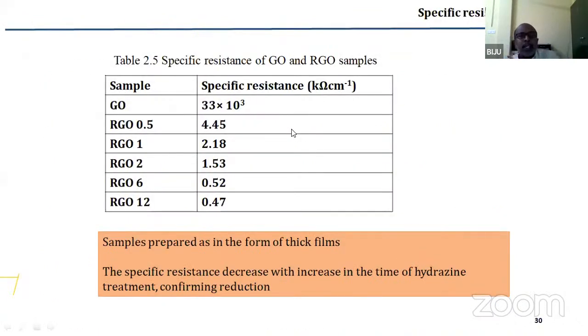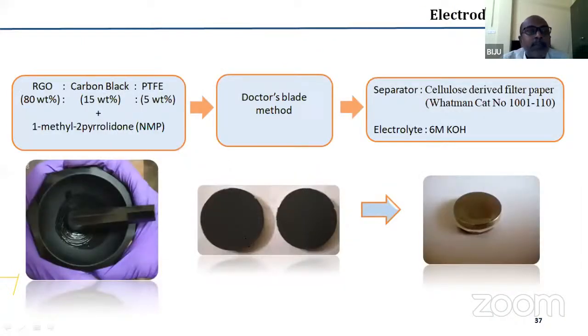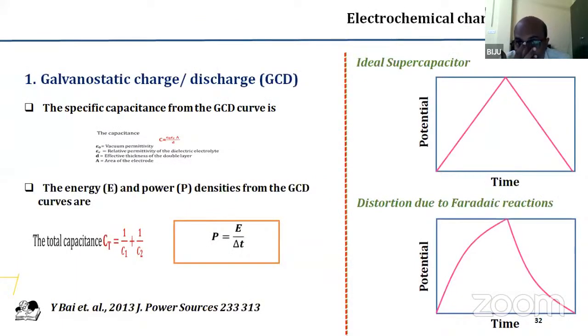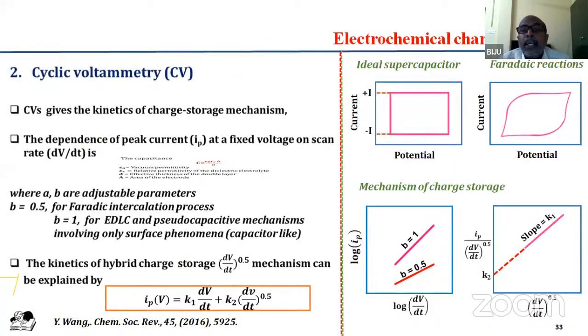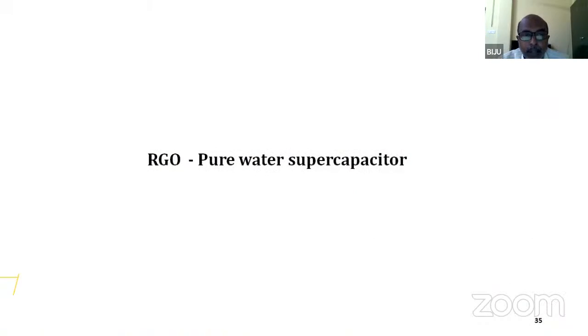Now the specific resistance of these samples was also measured, and as expected during reduction, the specific resistance gradually decreased because the graphitic layers were becoming more and more conductive. Now, the supercapacitor electrodes were produced in the very conventional way. The images are shown. I will skip the characterization techniques for supercapacitors. We use galvanostatic charge-discharge, cyclic voltammetry, as well as impedance spectroscopy to characterize the supercapacitors. The details I will just skip, and I will go to the result.